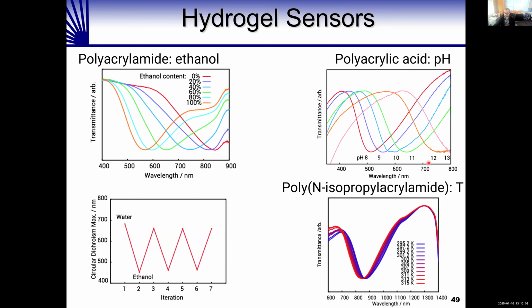So this is a very expensive pH sensor. We can also make them with poly-N-isopropyl acrylamide, which is a temperature-sensitive hydrogel that allows us to measure temperatures very close to the body temperature.